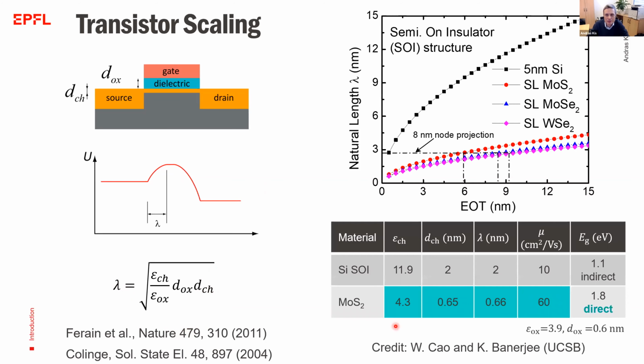And here using 2D materials brings several advantages. So it allows you to shrink the length of the transistor by shrinking the thickness of the semiconducting material, but it also allows you to relax a little bit the requirements, for example, on this gate dielectric by allowing you to have a slightly thicker gate dielectric and still have the same type of switching performance.